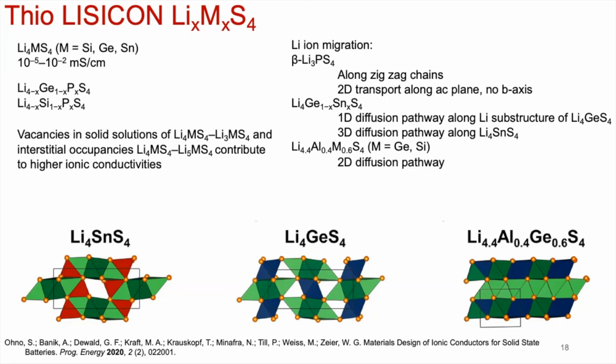The diffusion pathway is really interesting because with certain compositions, as you see here, it's 1D, as in there's a preferred pathway of high ion conductivity, and then in the two other directions, they're not as fast. Ideally you want high diffusion, right, in all directions. So there are some limitations to these types of compounds, because if you have 1D or 2D, you're going to be limited by how you orient your powders.